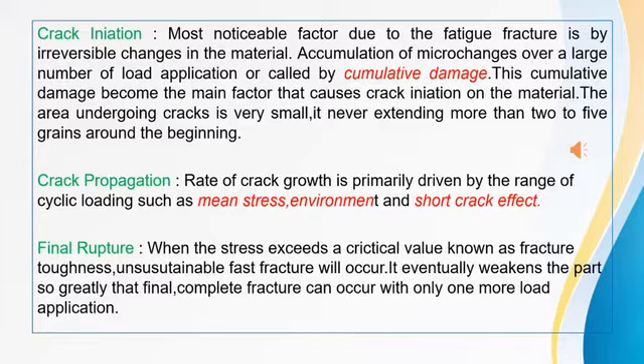If we consider the environment factor, the rate of growth becomes higher when the moisture is increased. For materials like aluminium, the crack can generally grow from the surface, where water vapor from the atmosphere is able to reach the crack and dissociate into atomic hydrogen. And the third factor is the short crack effect. Short cracks usually grow faster than expected.